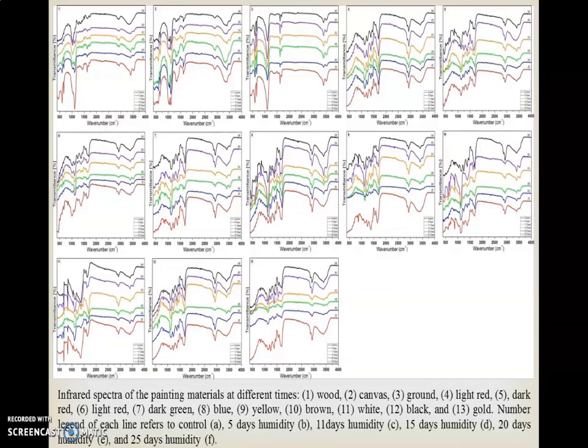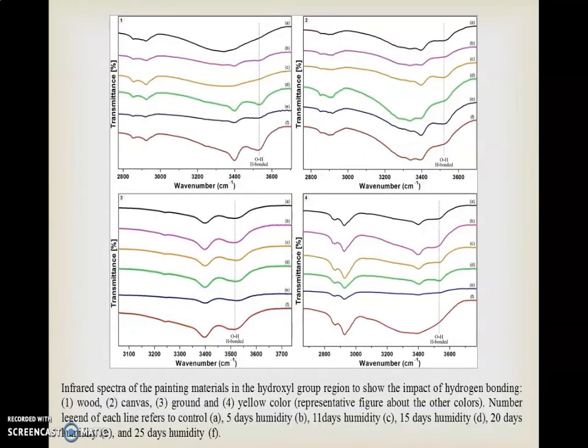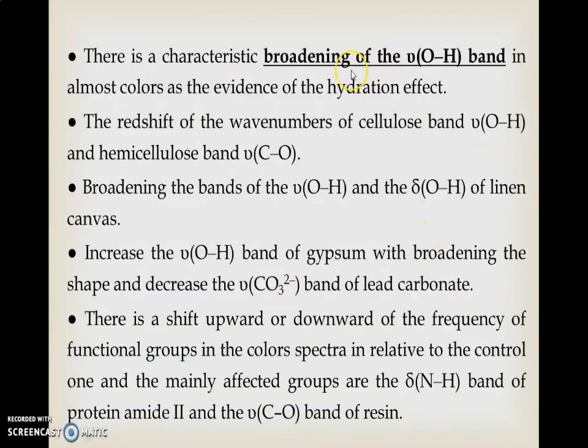Infrared analysis showed there were conformational changes within the painting materials, with a change of the vibrational frequency. There was a broadening of the OH group, H-bonded, with shorter bonds. There is a characteristic broadening of the OH band as evidence of a hydration effect. Also, for the wood, there is a redshift of OH and CO, cellulose and hemicellulose. For canvas, OH stretching and bending of OH. For gypsum, an increase of OH and a decrease of carbonate, of lead carbonate. Also, there was a shift upward and downward of the amide group of the binder animal glue, and the CO band of the resin.